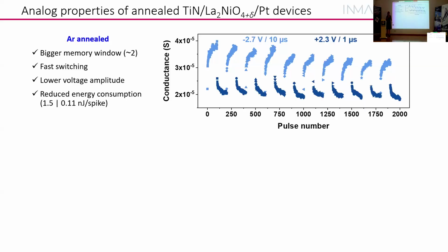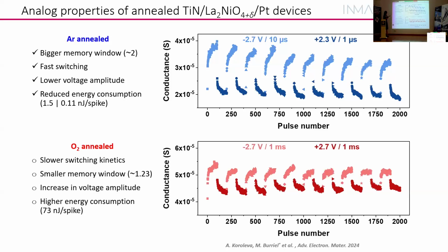We have to play a lot with the conditions of the pulses, the length of the pulse, the duration of the pulse, and these were the optimized conditions for the argon annealed samples, and these are the optimized conditions for the oxygen annealed samples. So when we couldn't get the filamentary switching, we have a lower window, slower switching kinetics, increase in the voltage amplitude, and higher energy consumption. So these ones, the argon annealed, clearly worked much better.